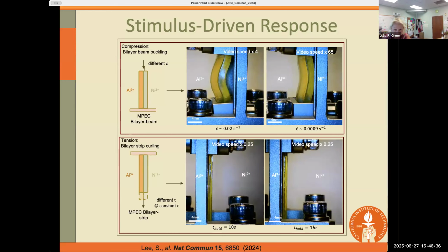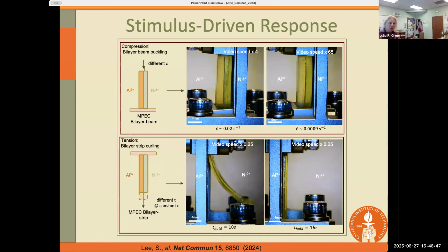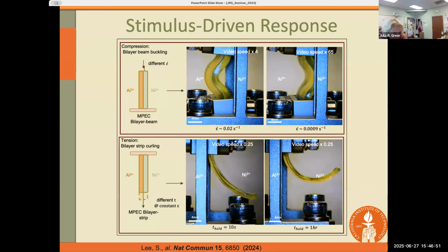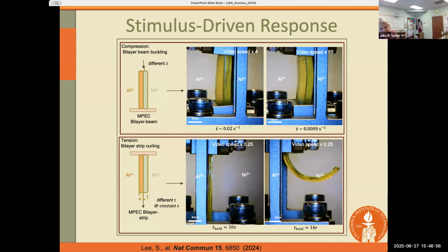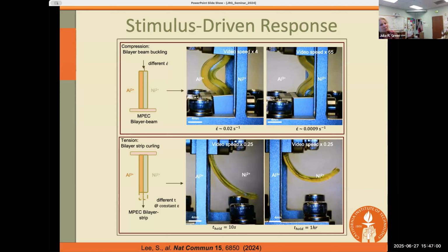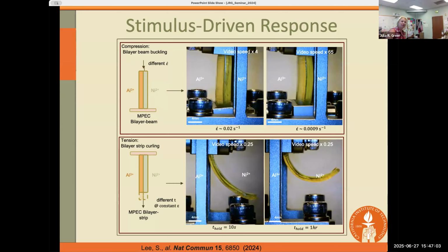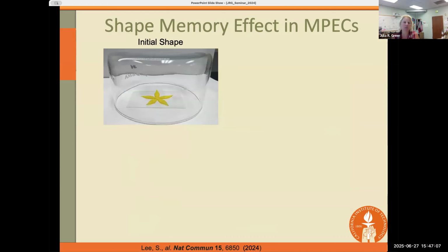In the next experiment, the so-called stress relaxation experiment, we effectively subjected this bilayer strip to a hold. We attached a load to it, and then we held it for 10 seconds. When we release the load, you can see that it's curling up. If we hold the same strip for an hour, it curls up to a much greater degree of curvature, a much tighter radius of curvature. That gives us a degree of tunability and responsiveness in these kinds of MPEC materials, which already represent a pretty unique set of materials.